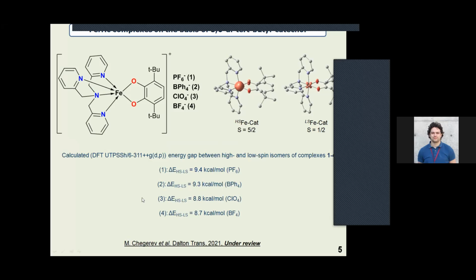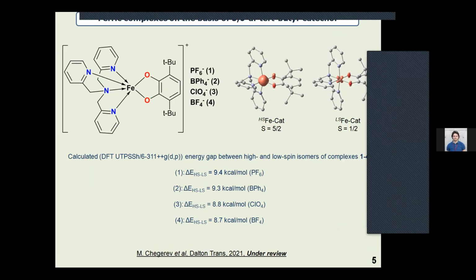Preliminary DFT results revealed the possibility of spin crossover in systems under consideration. According to calculations, the energy difference between low spin and high spin states does not exceed 10 kilocalories per mole, which, within this approximation, indicates a high probability of detecting the spin crossover.